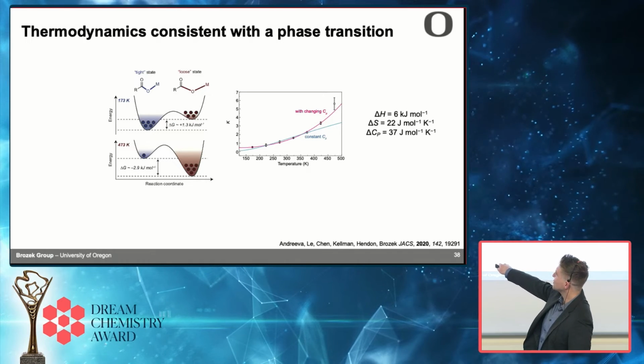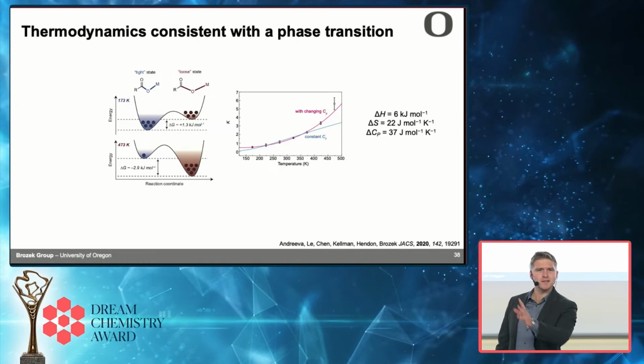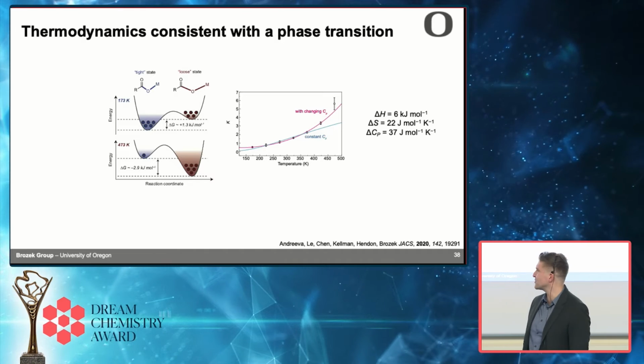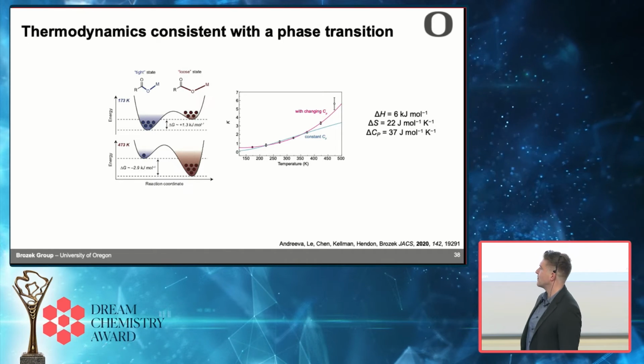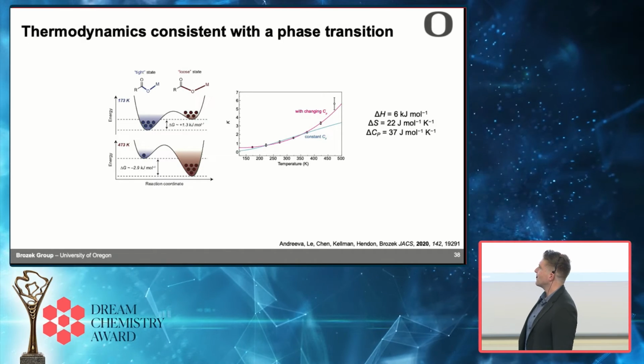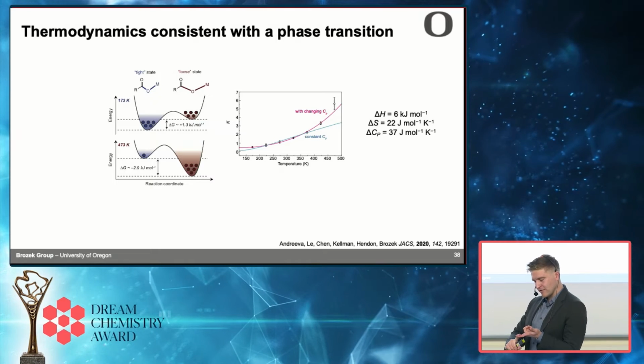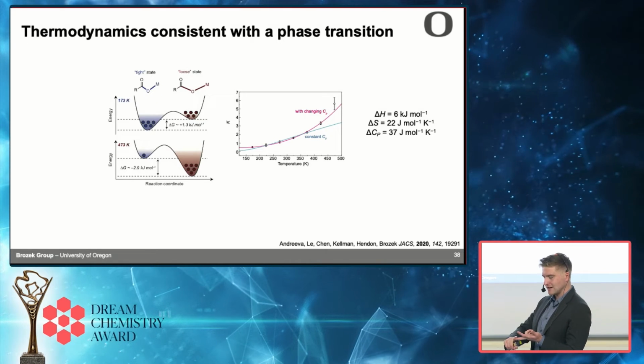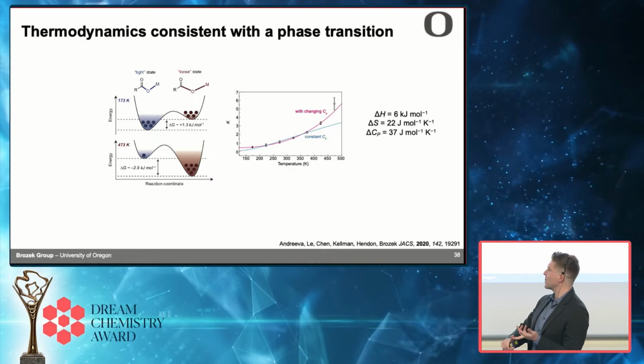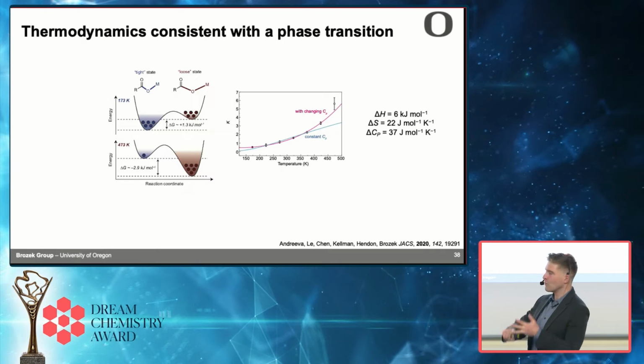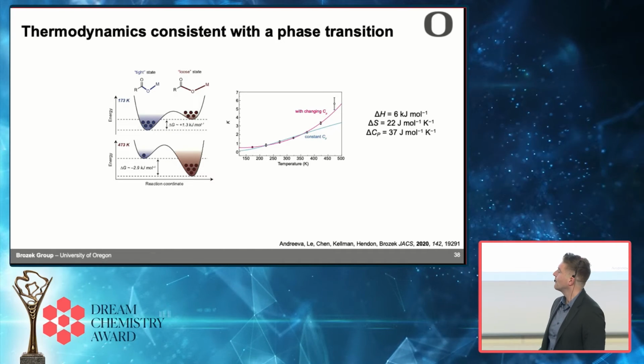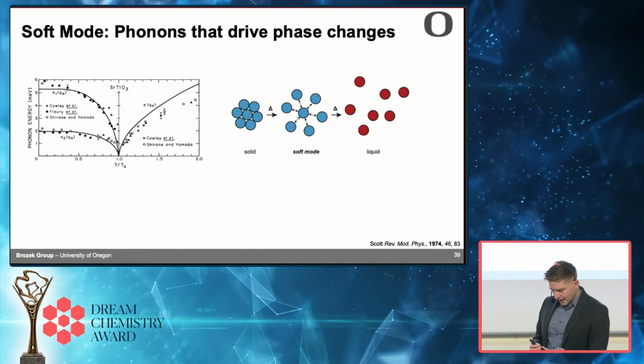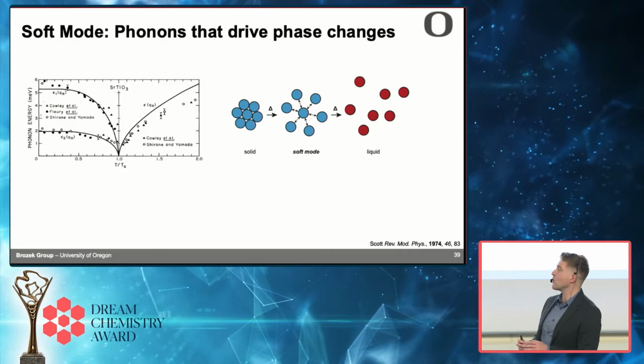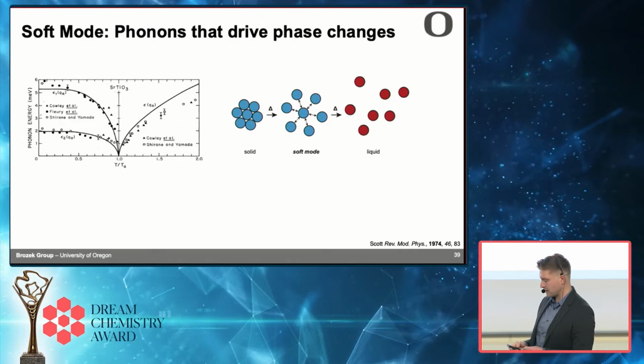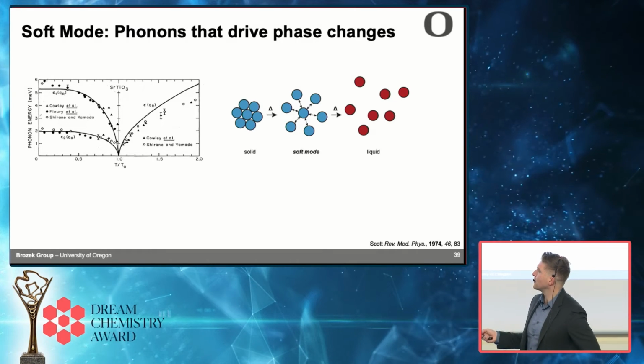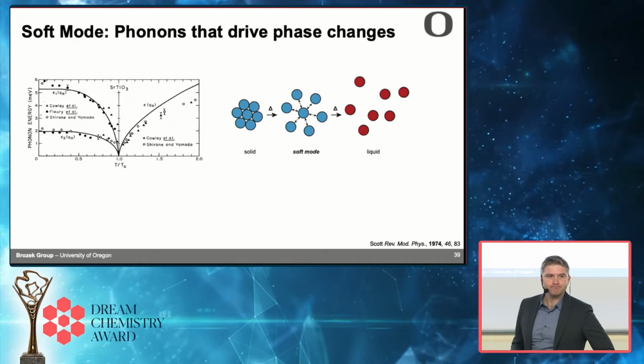The delta H and delta S values that we get out are also consistent with a phase change happening in this sort of system. And so you're wondering, okay, what do redshifting vibrations have anything to do with a phase change and this equilibrium? What's going on here? And so when we put this all together, we came across this idea that I didn't know about until we started on this project. And it's the idea of something called a soft mode.